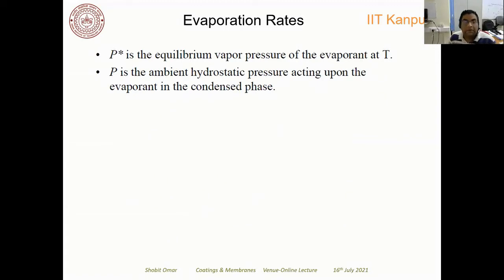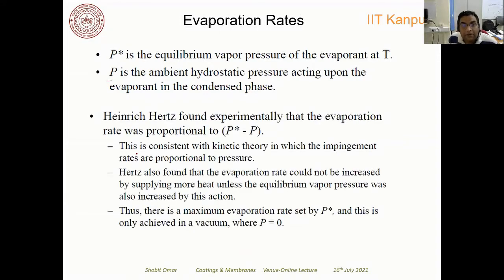Okay, so what I have shown you in the previous slide is P star. And let's say there is a hydrostatic pressure which is applied on the condensed phase from the evaporants, and that pressure is given by P. Okay. So Heinrich Hertz found experimentally that the evaporation rate is proportional to P star minus P.